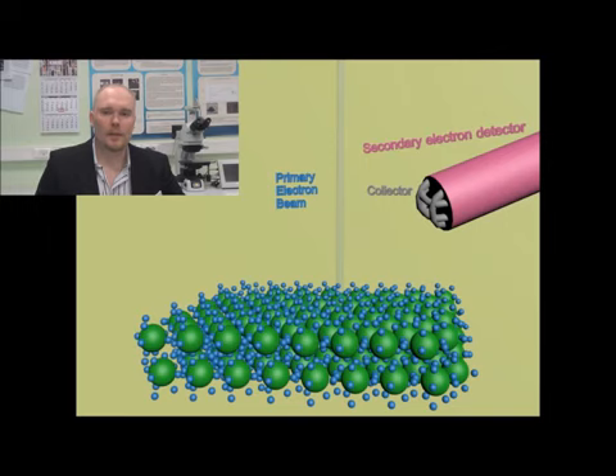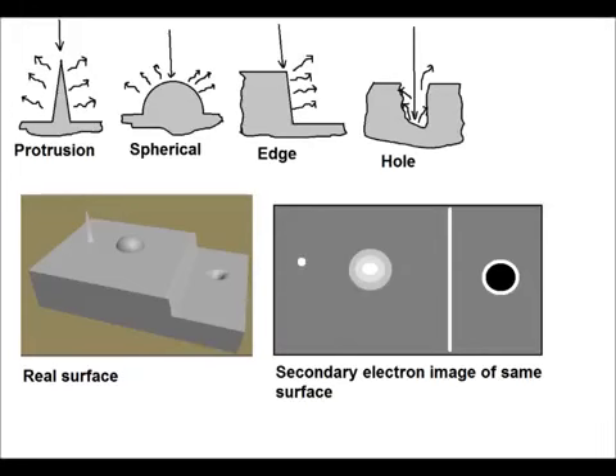After they have escaped the material, they will start moving towards the collector, which has positive potential. And once they have passed the collector, they will interact with the detector behind it, which is called the secondary electron detector. And by using this signal, we can create a secondary electron image of the surface which we are studying. The secondary electron images are black and white. The brightness of a surface detail on the image depends on the amount of electrons that have escaped it. The electron yield is larger on sharp protrusions, spherical areas and edges. However, deeper pits and holes will appear darker, as fewer electrons escape them.